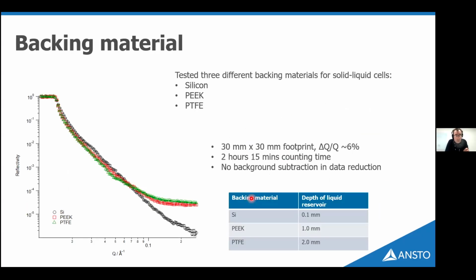Sort of going back to the background, so we've recently tested some different solid liquid cells that various people have provided us, and we do find that silicon does give us a much better background than PEEK and PTFE. But now we're just trying to weigh up whether we sacrifice some background to have some more robust cells at the moment is what we're trying to grapple with and trying to find a solution of, well, can we have both?